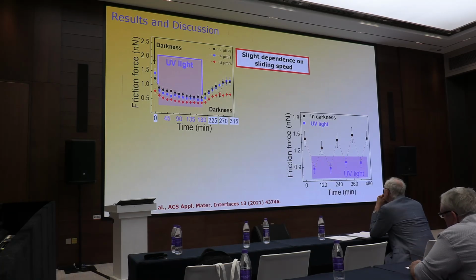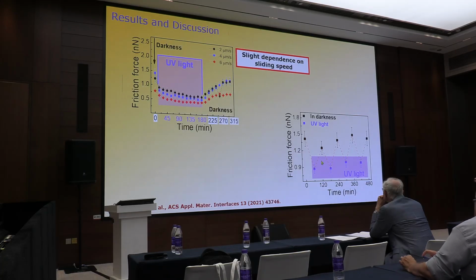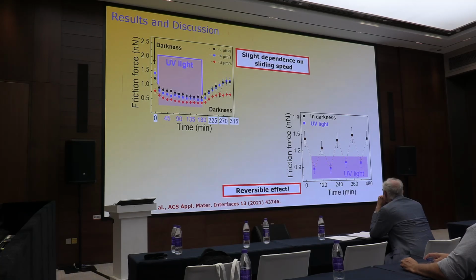Another point is this: this is in darkness and this is UV. We stop, and this is in darkness again, and the friction force increases. Then we turn on the UV again and there is a new reduction of the friction coefficient. Then we turn off the UV, in the darkness again, and the friction coefficient increases. This is a reversible effect. This is very important because for tribology we have to control the system. It's reversible and stable in time.